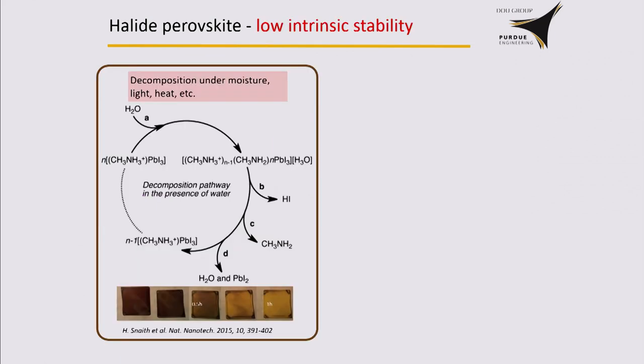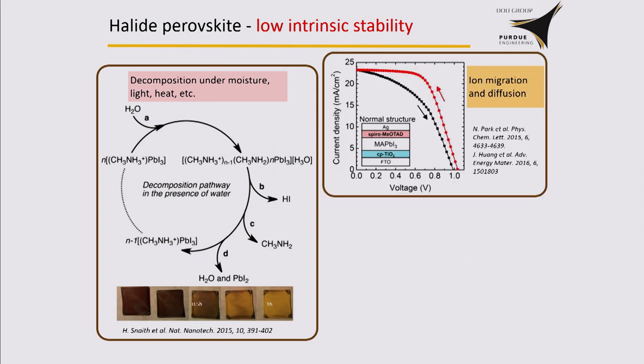The key problem is the intrinsic low stability. Because of the weak lead halide bond, it makes things soluble and easily processable. But at the same time, the weak bonding makes the material not very stable. So basically, it decomposes under all kinds of external stimuli, for example, moisture, light, and heat. In addition to chemical decomposition, there's another unique feature called ion migration or diffusion. You never see this in conventional semiconductor materials, but it's a big problem here in perovskite.